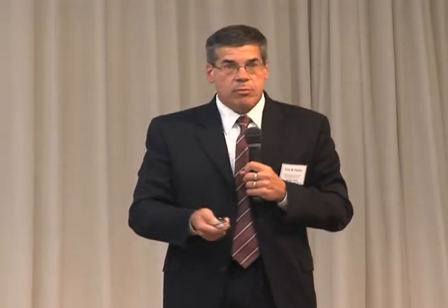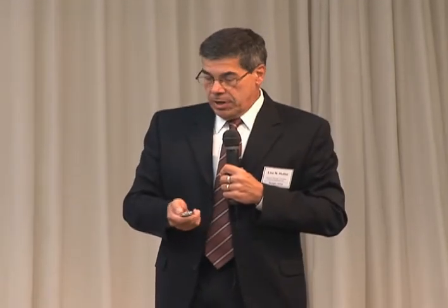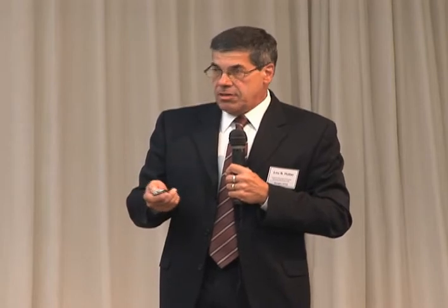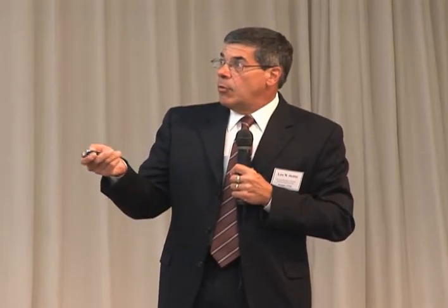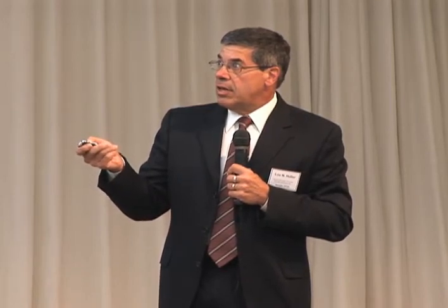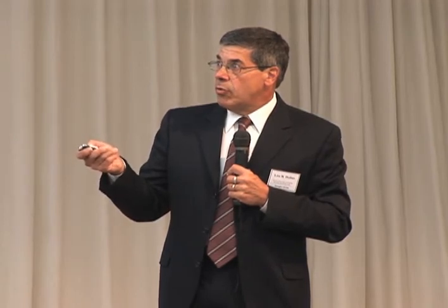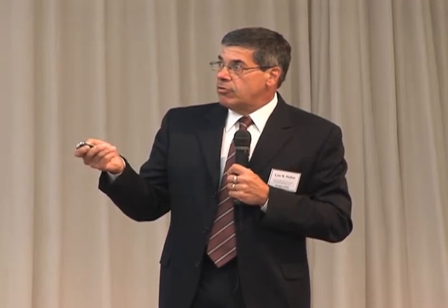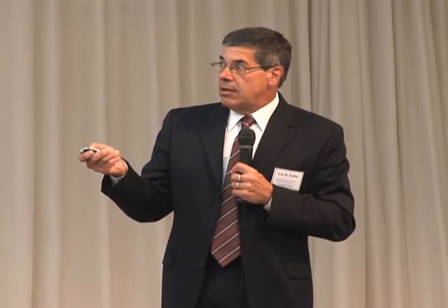So basically you need the Z direction for analog. We talked earlier about how FinFETs were going to become important for logic. Analog has a similar kind of need. We have a number of factors that impact density. STI and chemical mechanical polishing force density rules. Well dopings are getting too heavy, so that reduces our drain extended devices. Copper back end of line, we get dishing problems.